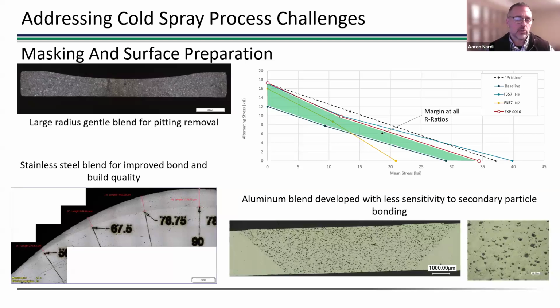Now, if you are spraying onto a more complex shape or into a more complex feature, that's where some of the alternative materials come in. So you see an image here, that same shaft that I was showing before being coated, from one direction in a raster pattern, but now you've got very good interface, you've got very good quality of your deposited material, and that's because of this unique blend that helps to create a very dense structure and well-bonded structure.